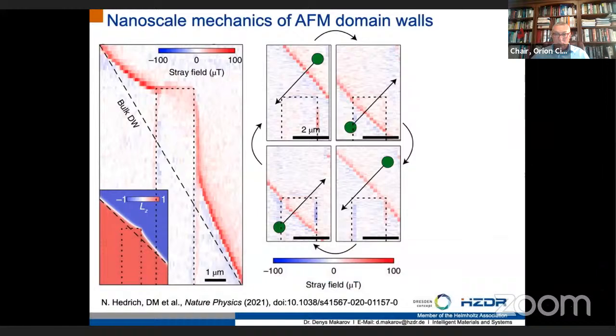Please pay attention to this left-hand side image. The domain wall in the bulk is shown with a dashed line. It's the equilibrium position of the domain wall. Now you can use the laser light from the NV microscope to drag the domain wall from this equilibrium position and simply make it pin at the edge of the meso. There are two important characteristics which are recognizable in this image. First of all, the domain wall can be elongated substantially. It's displaced several micrometers, as you can see on this image. Another aspect is that the domain wall follows very precisely the very sharp edge of the meso.